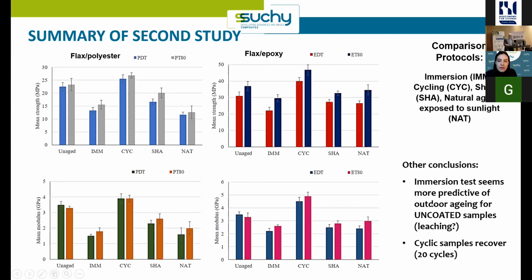So the water can really get into the fiber and also cause leaching maybe of ingredients in your fiber. And of course, with a good barrier coating, you could hopefully prevent that. And then maybe you would more go back to the cyclic moisture situation. And there it was actually very surprising that initially we had damage and we saw a decrease, but eventually we saw quite an increase in the properties after cyclic loading. So that is clearly something we need to do further research on.